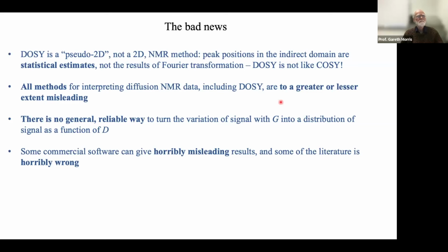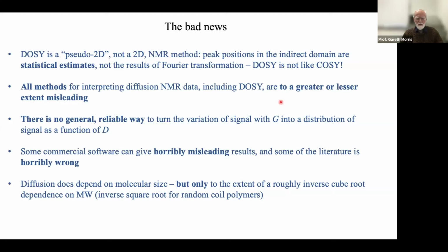And then finally, just to cap it all, diffusion NMR tells us about diffusion coefficients. But usually as chemists or biochemists, or even structural biologists, what we want to know about is molecular weight. We want to know about size. And the rate at which a molecule diffuses through solution effectively depends on its hydrodynamic radius. And that for a globular molecule, like a globular protein, depends on the inverse cube root of molecular mass. But even for a random coil polymer or a fully disordered protein, it's still an inverse square root. So for a big difference in molecular weight, we get a not so big difference in diffusion coefficient.